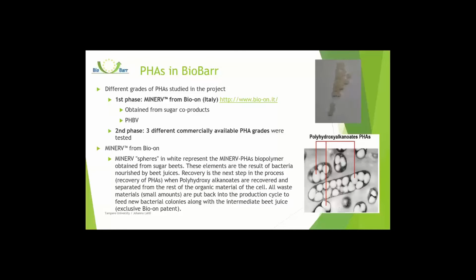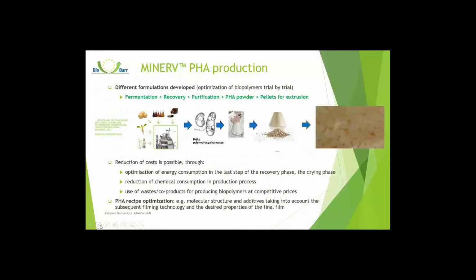There is here some information on the Minerv grade from Bio-on. So they first produce the PHA powder, and then they formulated the powder into pellets or granulates that we then processed at Tampere University. The process in the beginning was already a little bit explained in the introduction presentation, but everything starts from fermentation. Then we have the recovery phase, purification, and then we have the PHA powder, which was then modified into pellets that we used in our extrusion process.